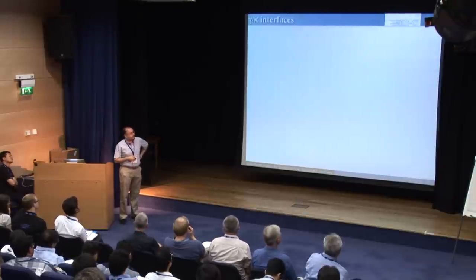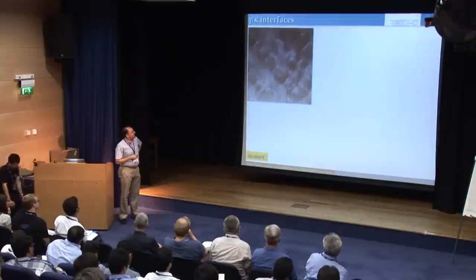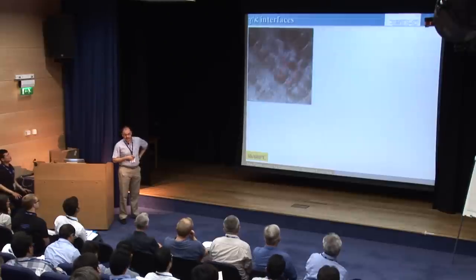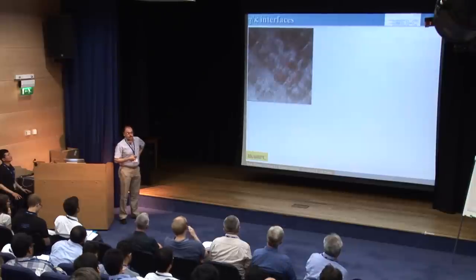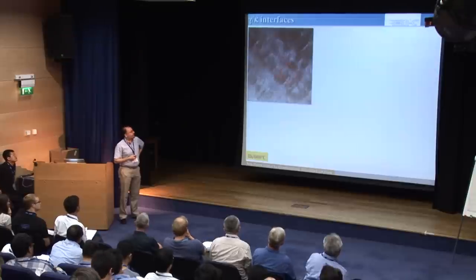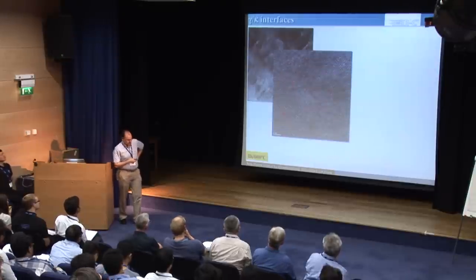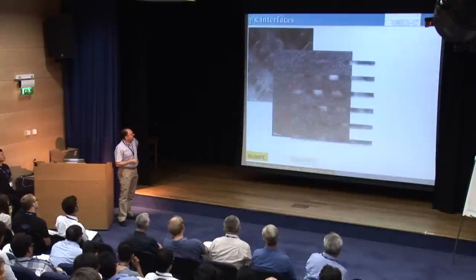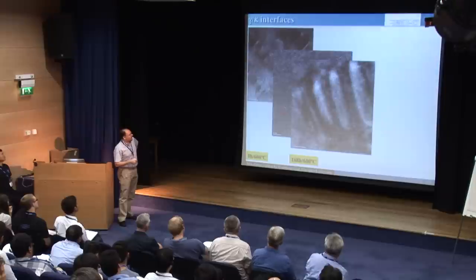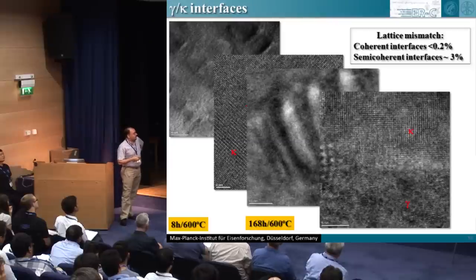So understanding gamma-kappa interfaces, this is an ongoing collaboration with Ruska and Jülich. We are running a high-resolution microscopy analysis of the interfaces. We are interested in determining the crystal structure of the kappa, and what's more interesting is the lattice mismatch. So we want to understand much more clearly the nature of the interfaces, and later on, upon the formation. This is some early preliminary analysis of the gamma-kappa interfaces at different annealing times. These are plate-type particles.